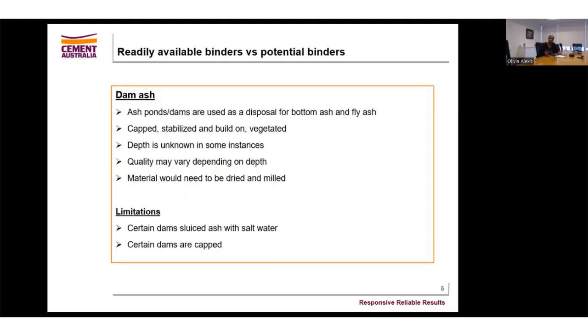So if we look specifically more into a readily available binder such as dam ash, I've considered dam ash to be readily available for one particular reason, and that is because the material is there in the ground and can easily be reclaimed, or can easily be processed at a very low investment cost. So the material basically needs to be taken from the ground, dried and milled. Just a bit of background on dam ash: there is an extensive amount of fly ash and bottom ash in dams right next to a lot of power stations. Power stations have been pumping bottom ash and fly ash into dams for many years for different reasons. Some of these reasons could be high LOI that doesn't necessarily meet the requirements, or it could just be a lack of space and having to put it into dams.